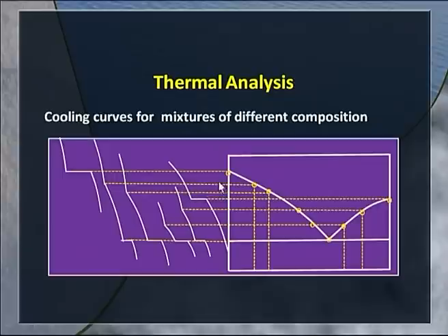If you take various mixtures, you can get the point of initial solidification to have this point. Similarly, initial solidification, you can have a point on the curve, and in the case of mixtures you will always see that you have the flat portion corresponding to the eutectic temperature. So all will show this, 1, 2, 3, whatever mixtures that you have taken.